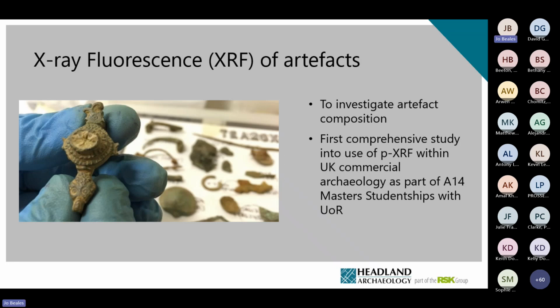As part of the A14 project, again, we did a comprehensive study. It was part of the master's studentship that Gemma Morehouse did, working with Pete, on a large number, over 450 objects I think it was, of copper alloy objects from the A14, with lots of really interesting results. There seemed to be a very distinctive regional pattern to it. There was increased use of a wider variety of alloys throughout the Roman period, and a greater incidence of recycling in the later Roman period, amongst other things. So it was really important.